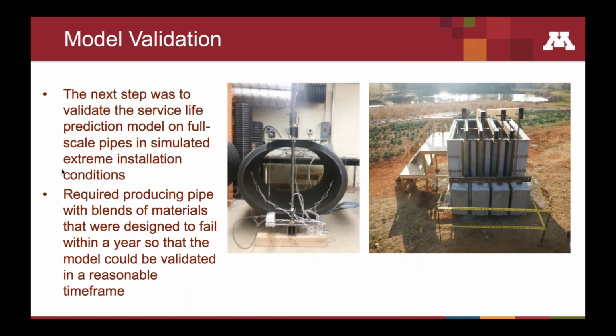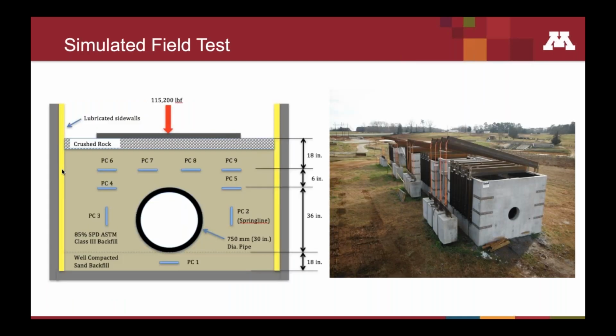One, in the laboratory, by installing some pipes under very, very high deflections and high stresses, much higher than what would ever be observed in the field. And then secondly, by doing the same thing in a simulated field test, as shown in the right picture, where we basically compress the pipes under very, very high loads with very poor backfill conditions to see how long they would last in that condition.